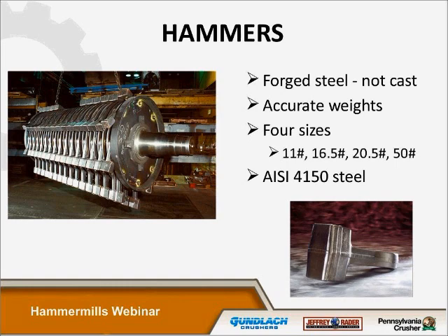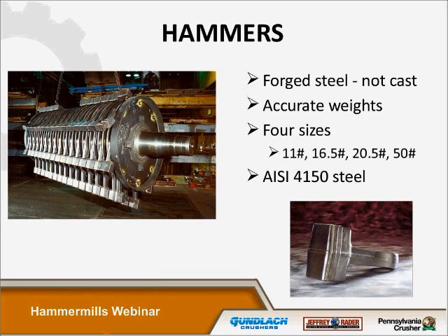Hammers vary in size depending on the crusher size. This is a typical PCC hammer mill hammer — a forged steel hammer, differentially heat treated so that the head is hard but the shank is more ductile. The working face of the hammer is about 450 to 500 Brinell hardness, while the shank may only be 300 Brinell, providing a hard working face with a ductile shank that's forgiving of uncrushable material. We can also apply tungsten carbide hard facing to the working face in several different arrangements.